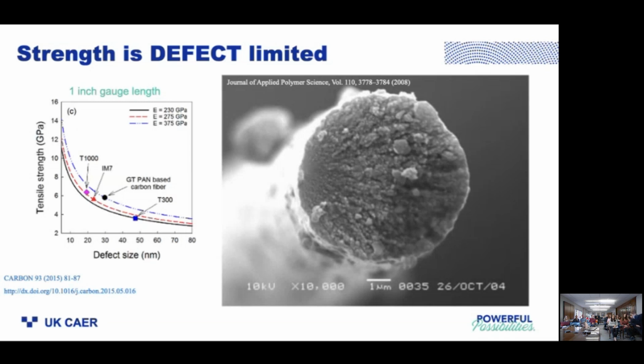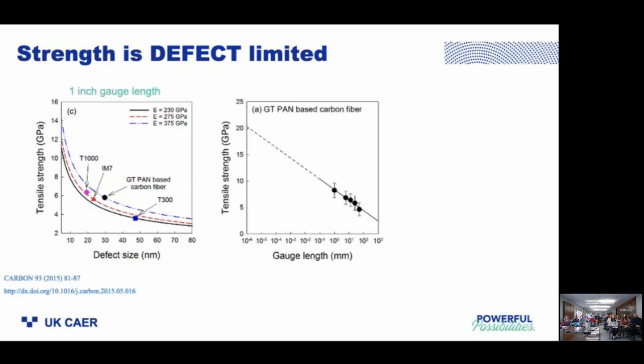That's the strength limitation. If you extrapolate that further, you can see that if we consider a defect that would be 1 nanometer, those strengths would be predicted to be somewhere on the order of 20 gigapascal, which is in fact what Bacon observed in 1959. But achieving that over long lengths, over long scales, is the real heart of the manufacturing challenge of carbon fiber to achieve high strength carbon fiber.